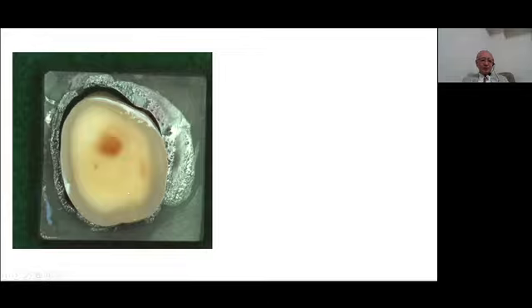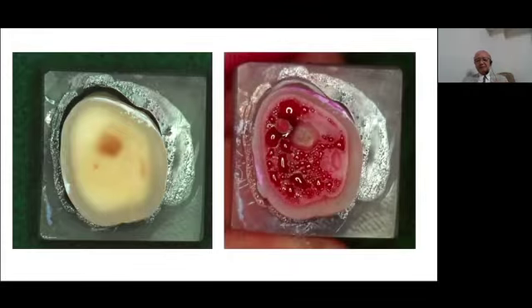This is the occlusal view of the same specimen. This caries region should be removed before the restoration in the clinical situation. I removed this caries region and I put a pressure from the pulpal side to squeeze the red dye solution. Now you can see that. Here you can see the red dye solution infiltrated from the pulp chamber through the dentinal tubules. But in the area of the caries region, after the removal of the outer caries region, no fluid comes up, this part and this part.